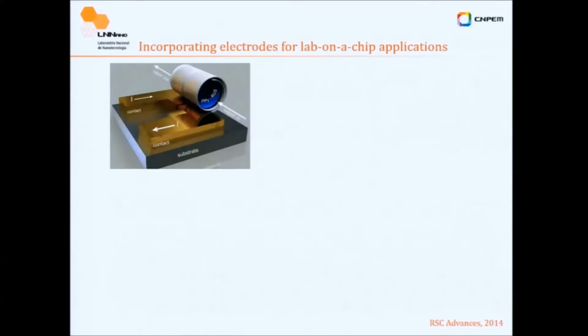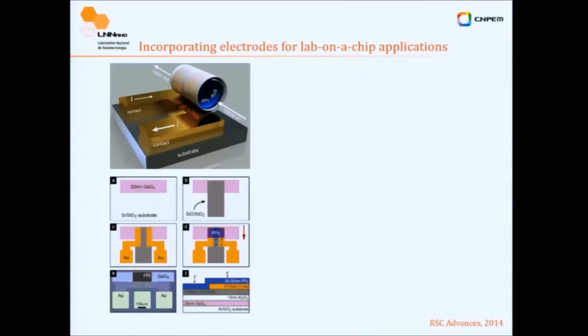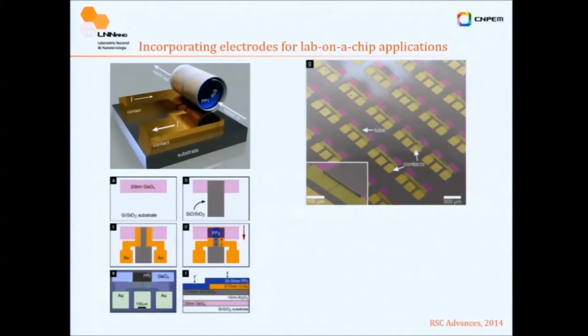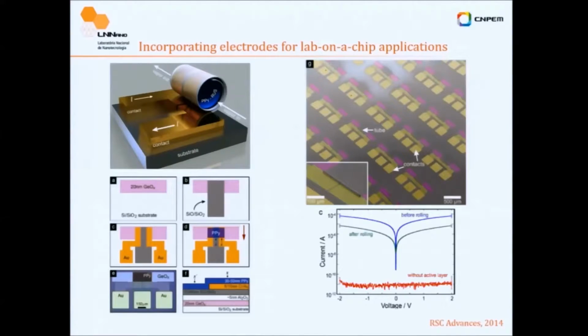Okay, we made a little bit more development on how to place the contacts inside, we developed a new process, and what you have in the end is an array of several tubes where we have two contacts and the polypyrrole inside of the tube. You can see this IV trace. Before rolling, you can see the polypyrrole conducting. Here, after rolling, it drops a little bit more. The reason is that we roll in water, you remove the counter ions, the material gets a little bit insulating, and then you put a little bit of HCl and you can recharge the system, but never as good as before.